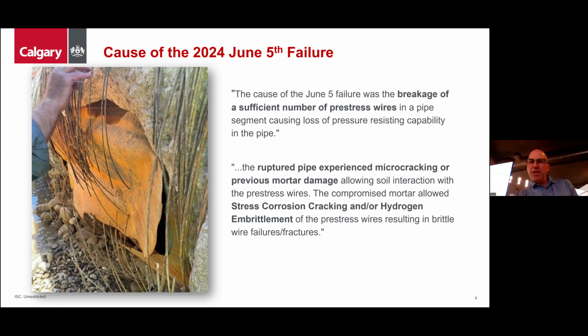Based on the information available, we believe that the ruptured pipe experienced micro cracking or previous mortar damage, allowing for soil interaction with the pre-stressed wires. If you're familiar with the construction of PCC pipe, micro cracks are small cracks within the outside mortar layer that are invisible to the naked eye, but still allow the external environment to become in contact with the wire wraps.